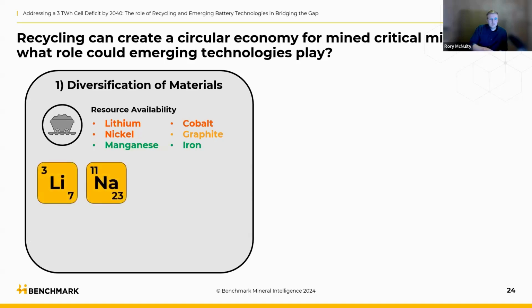As we look to alternatives for lithium, sodium is the one that's often brought into the conversation. Now, sodium-ion batteries have been developed for about as long as lithium-ion batteries. However, it's taken them a bit longer to find their commercial footing. We've seen really quite significant progress in China over the last few years. We've seen rollout of early sodium-ion batteries, but really they're still finding that commercial drive and commercial push, especially in the new price environment of lithium-ion batteries. But the dawn of sodium-ion batteries could alleviate some of that stress on lithium-ion supply, and we'll explore that a little bit later on.